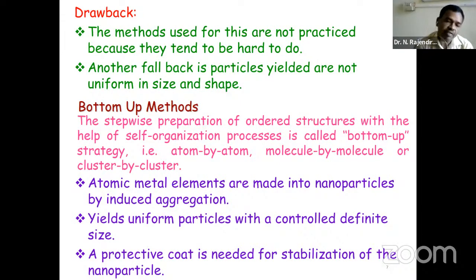Whereas the bottom-up approach uses chemical methods, that is, self-assembly and growth stages, where the metal nanoparticles join together in a growth process. So we can control the size and the shape of the particles at any point. As a result, the prepared particles will be of uniform size because of atom by atom, molecular, or cluster by cluster association. So at the end of the reactions, you will get uniform-sized nanoparticles. The atomic metal elements form nanoparticles by induced aggregation, yielding uniform particles with controlled, definite size, and protective coats are needed for the stabilization of metal nanoparticles.